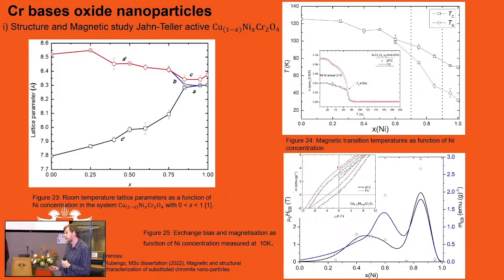And then what you find was very exciting. You suddenly find what's called exchange bias, the graph at the bottom to the right. If you go and measure the applied magnetic field and you measure the magnetization, you look at the loop, you can clearly see a shift in the loop. It does not center around 0, like you would expect a theoretical ferromagnet. And we saw this as exchange bias.